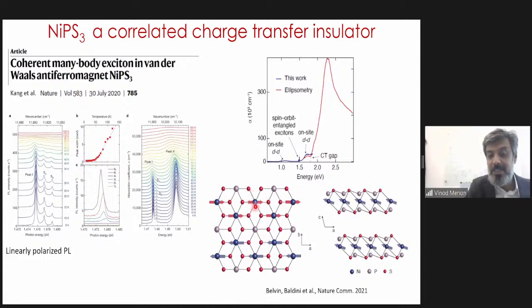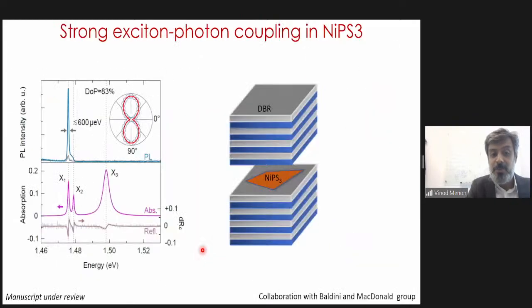And the result is that they're very close to each other, the electron and the hole, but the wave function overlap is not large enough that you get a good oscillator strength. So that's our current understanding. It's still an open debate. And so we were able to show the strong coupling.